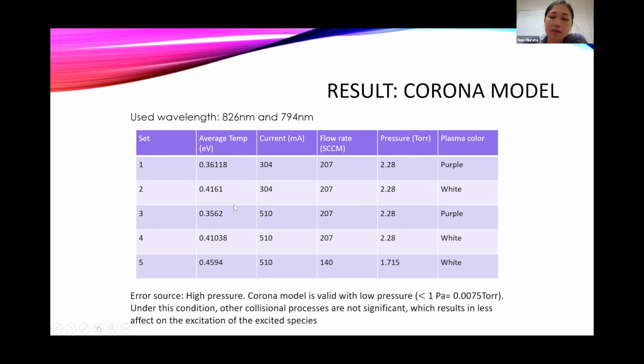However, when we analyze this data, we see one characteristic, which is white plasma has higher temperature than purple plasma. When we see set 1 and set 2, set 2 has higher temperature than set 1, and set 2 is white plasma. Similarly, set 4 has higher temperature than set 3, and set 4 is white plasma, and set 3 is purple plasma. So this is one thing we can tell from this result.